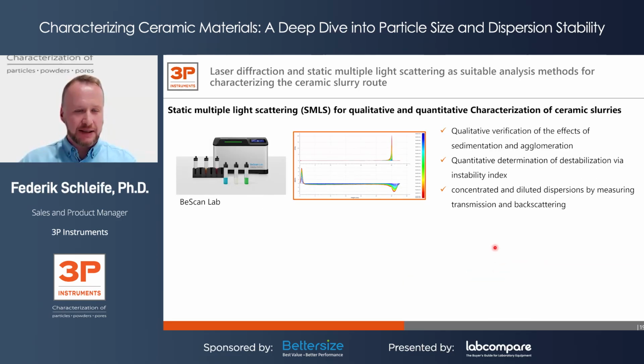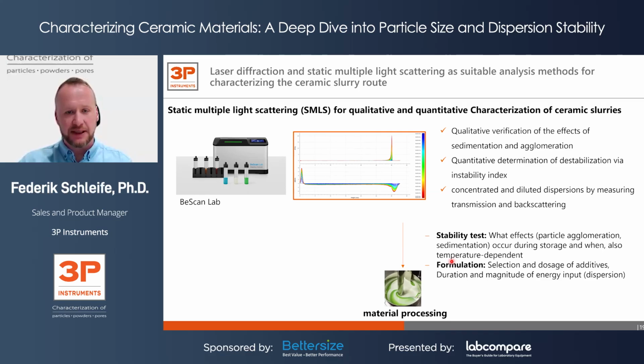And to analyze the dispersion stability, there's one technique that is widely used, static multiple light scattering, for the qualitative and quantitative characterization of ceramic slurries, which you will see in the second part with the B-scan lab. With the B-scan lab, you can analyze sedimentation and or agglomeration behavior of those slurries in a great way. So it gives you really a qualitative verification of the effects of sedimentation and agglomeration. It allows you to quantify those destabilization effects via the so-called instability index, and it offers you even concentrated and or diluted dispersions by measuring in transmission and backscattering. So this is mainly the stability test for the finer ceramic slurry.